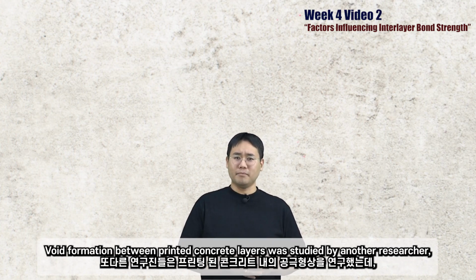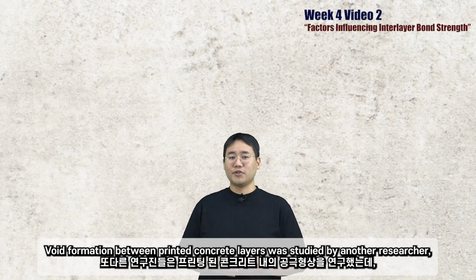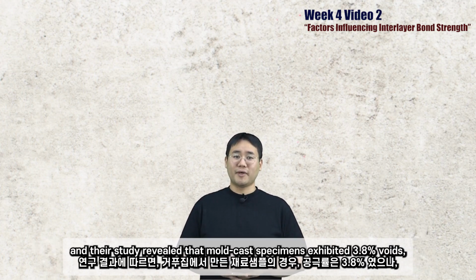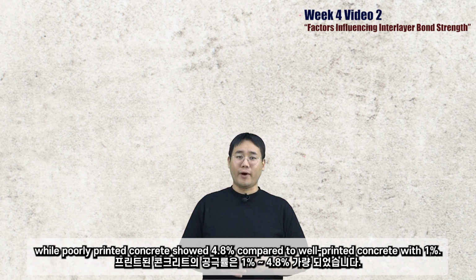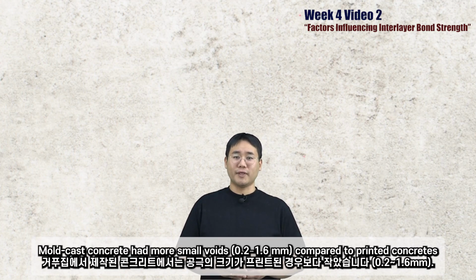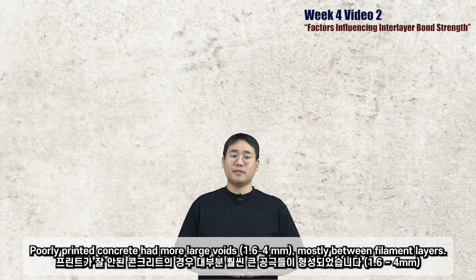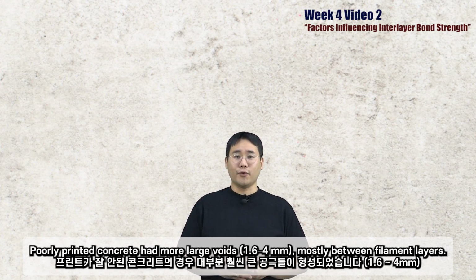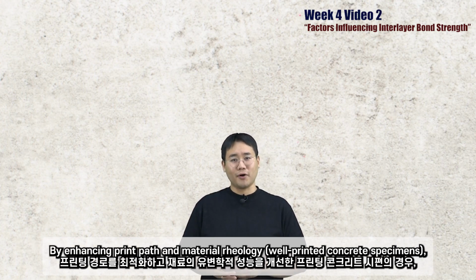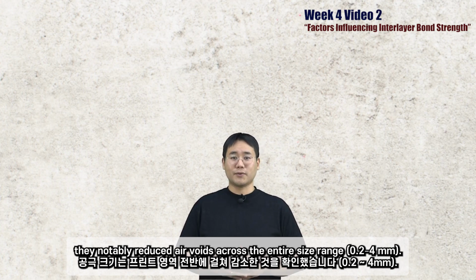Void formation between printed concrete layers was studied by another researcher, and their study revealed that mold-cast specimens exhibited 3.8% voids, while poorly printed concrete showed 4.8% compared to well-printed concrete with 1%. Mold cast concrete had more small voids, like 0.2 to 1.6 millimeters, compared to printed concrete. Poorly printed concrete had much larger voids, like 1.6 to 4 millimeters, mostly between filament layers. By enhancing print path and material rheology, in the case of well-printed concrete specimens, they notably reduced air voids across the entire size range.